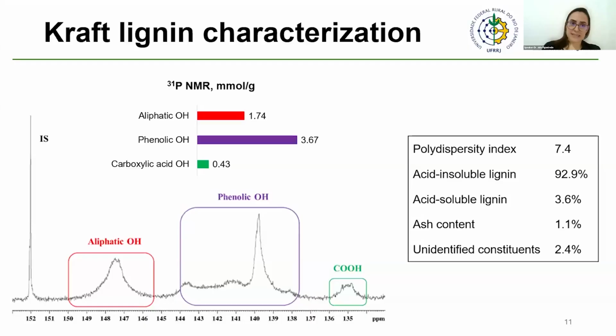And when we look at the phosphorus NMR, although both aliphatic and phenolic hydroxyl groups can react with the isocyanates, aliphatic groups are more readily available, and their interaction with the isocyanate is easier, if you can say so. Since the samples showed a high concentration of phenolic OH groups, the catalyst was essential to facilitate the reaction. That's why we used it to produce the polyurethane.